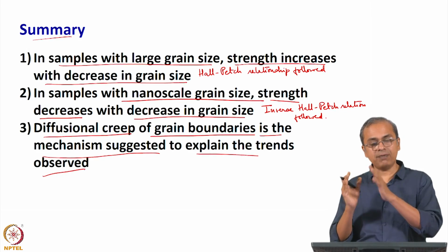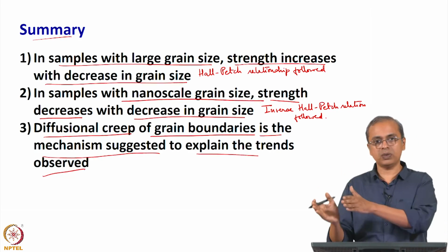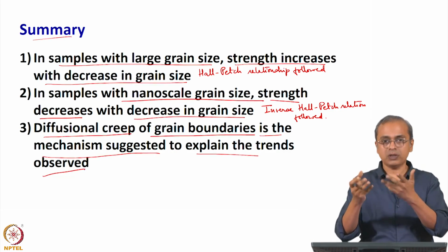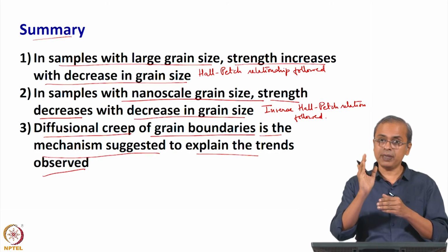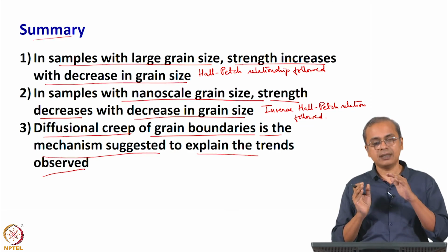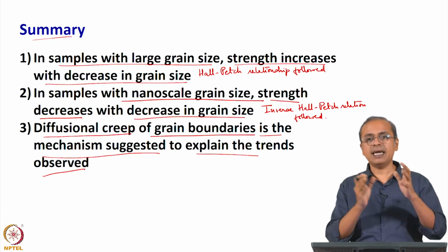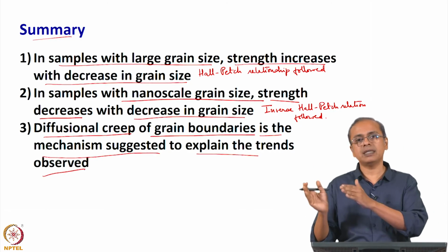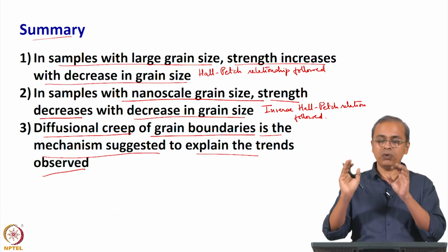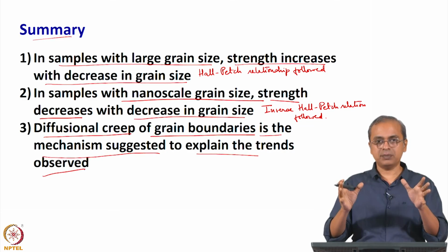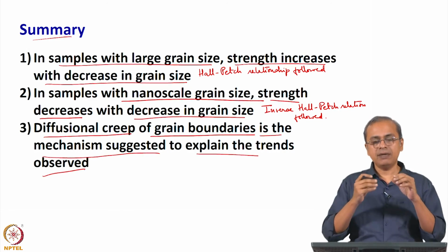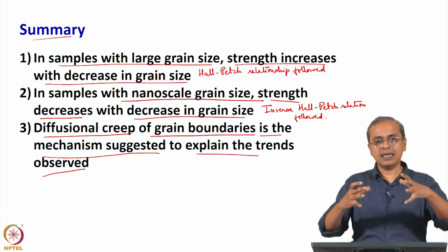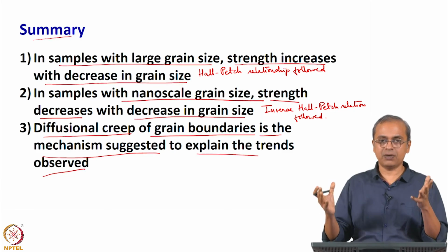So, atoms and vacancies can move through the grain as well as through the grain boundary. Generally, there are more defects at the grain boundary because there are incomplete bonds. Therefore, the movement of atoms along the grain boundary is typically faster than it is through the grain. However, in typical materials the amount of grain boundary that is available is less. Therefore, if you total up the number of atoms that are diffusing through the system, the fraction that diffuses through the grain boundary is less than the fraction that diffuses through the grain, and that is how you see the overall diffusion coefficient of that material.